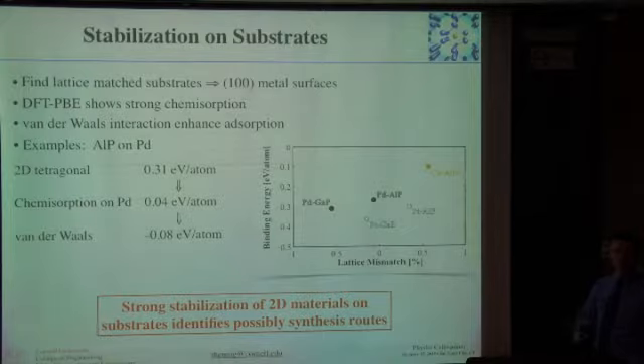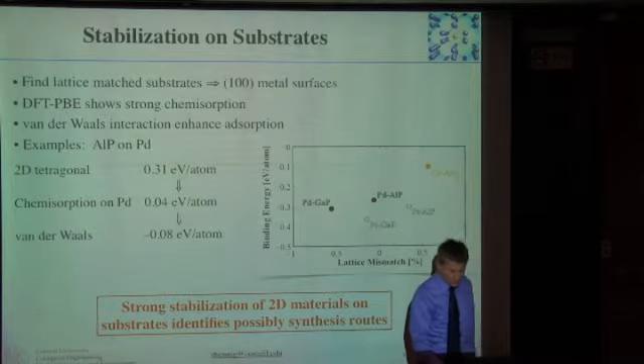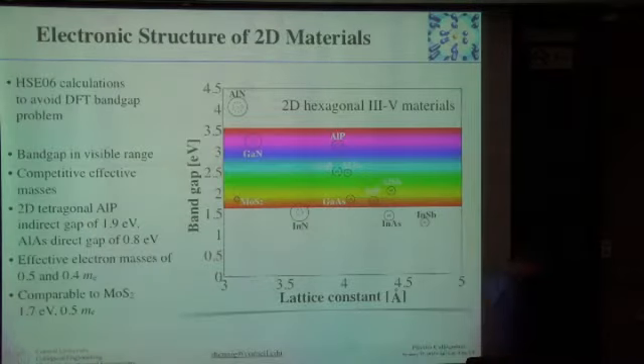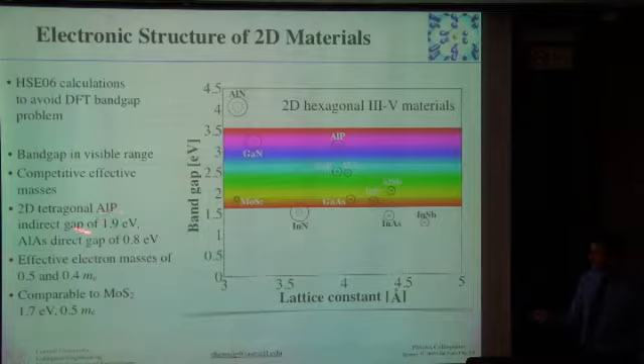So what we predict is you should be able to grow aluminum phosphide on palladium and get that to be energetically stable. There's a couple other substrates which should do similar things for that case. Then if you look at the electronic properties of that specific material, it has a good band gap, 1.9 electron volt. That's actually a very reasonable band gap for many applications as a semiconductor. That's much better than, for example, boron nitride, which has a band gap of something like 6 electron volt, completely useless as an electronically active material. This may actually be an interesting electronically active material, an alternative to molybdenum disulfide, which has a similar band gap.